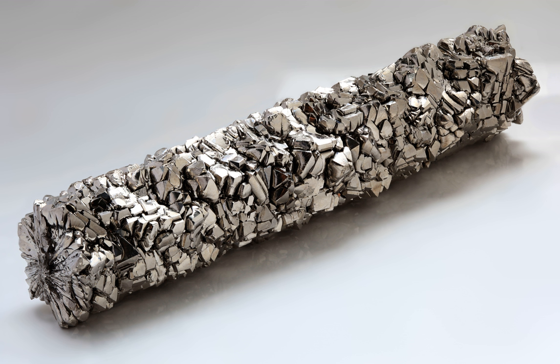However, titanium loses strength when heated above 430 degrees Celsius, 806 degrees Fahrenheit. Titanium is not as hard as some grades of heat-treated steel. It is non-magnetic and a poor conductor of heat and electricity. Machining requires precautions because the material can gall unless sharp tools and proper cooling methods are used. Like steel structures, those made from titanium have a fatigue limit that guarantees longevity in some applications.